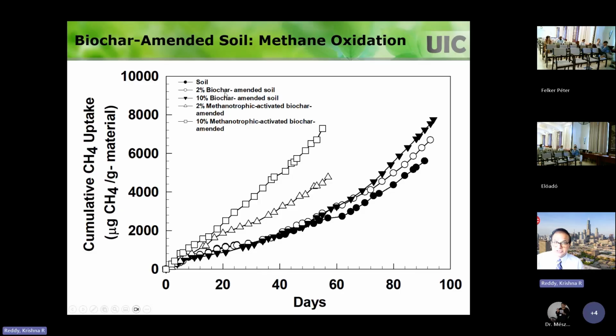But if I add 2% biochar to the soil, you can see there is not much difference initially. Later on, once the microbes acclimate to the biochar, you can see the rate of removal increases. And if I add more biochar, 10% biochar, you can see again in the beginning this acclimation stage, and after that, you can see it will take off. The initial acclimation period is important.